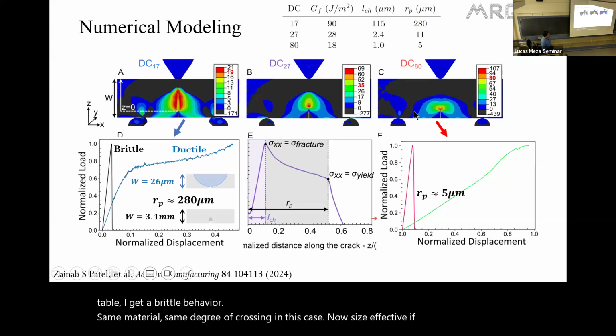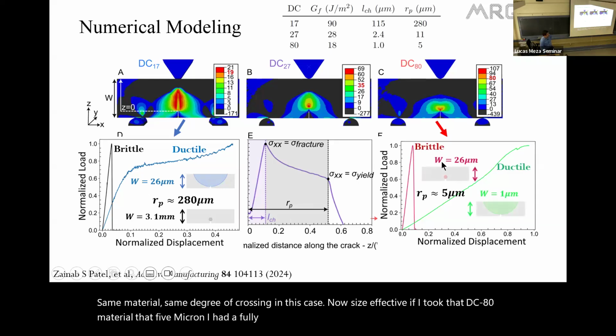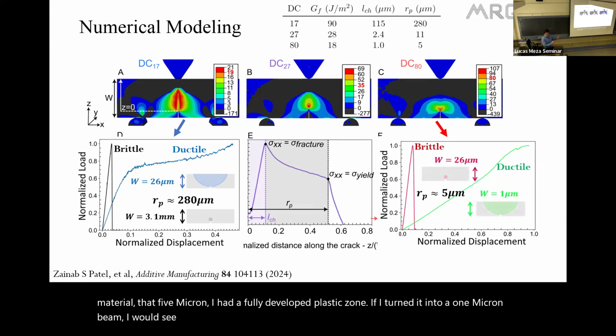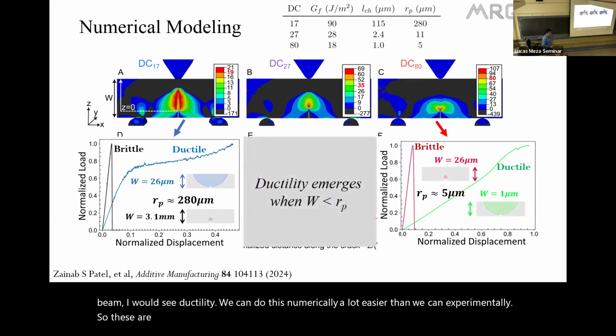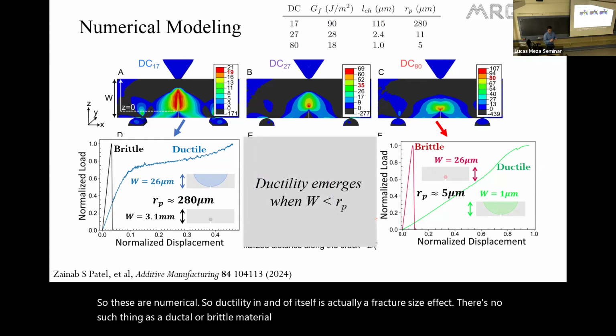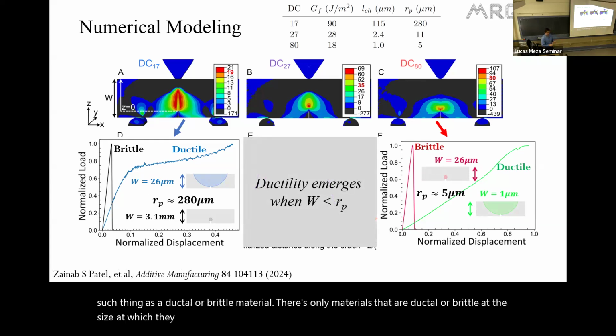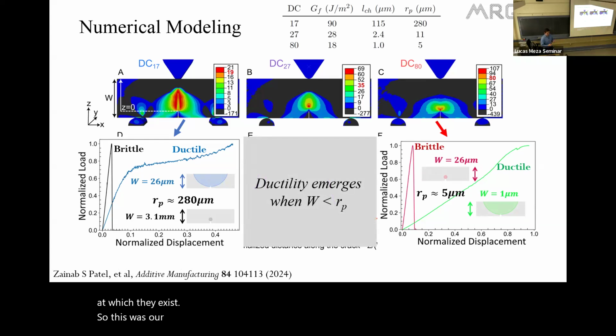If I took that DC80 material, that 5 micron, I had a fully developed plastic zone. If I turned it into a 1 micron beam, I would see ductility. We can do this numerically a lot easier than we can experimentally, so these are all numerical. So ductility in and of itself is actually a fracture size effect. There's no such thing as a ductile or brittle material. There's only materials that are ductile or brittle at the size at which they exist. So this was our rethinking ductility.